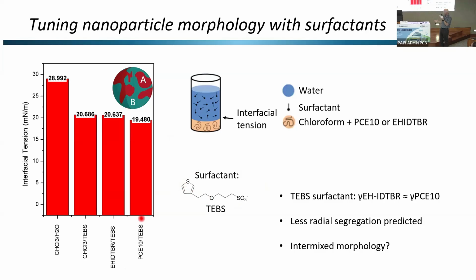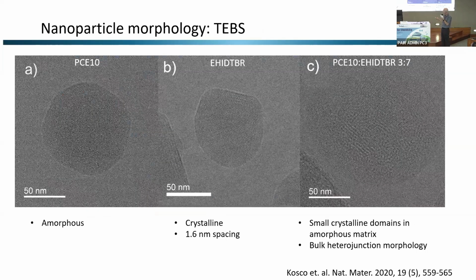But the interesting thing here now is that there is a difference in surface tension between our donor and acceptor when we add the TEBs, but not much. Remember, in the previous case, it was twice the interfacial tension for the acceptor and the donor. Here, it's maybe a factor of 10%, not that much different. So now we're expecting less radial segregation. So there's the opportunity, if we get phase segregation, that it can be quite random around the particle. And indeed, that's what happens.